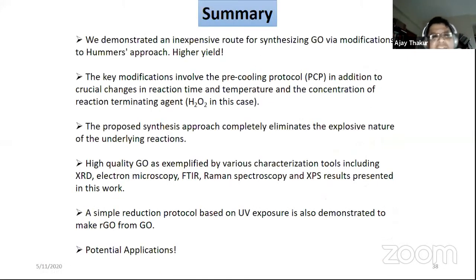So to summarize, we demonstrated an inexpensive route for synthesizing graphene oxide via modification to Hummers' approach. The key modifications involved a pre-cooling protocol and also a number of changes in the overall reaction parameters, reactant conditions, etc., which those who are interested can refer to in our paper. And this proposed synthesis approach completely eliminates the explosive nature of the underlying reactions.